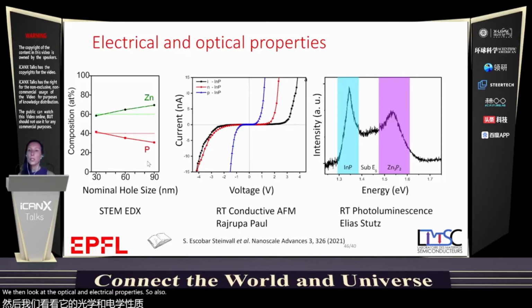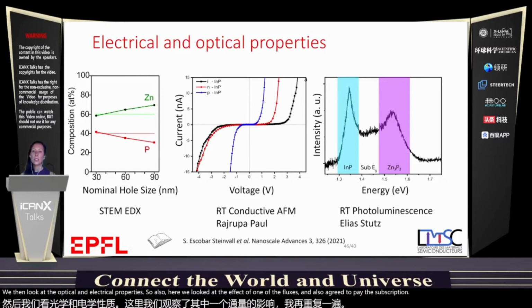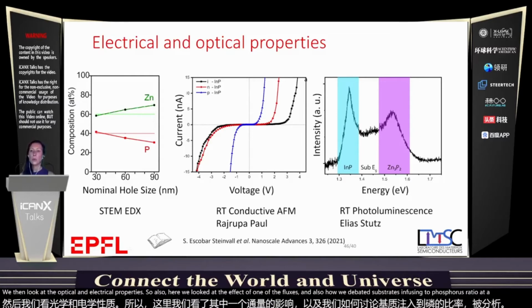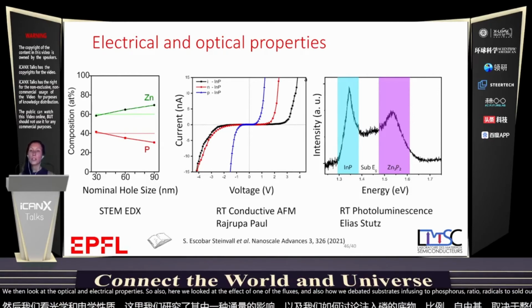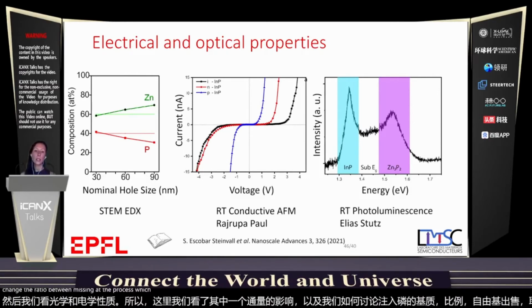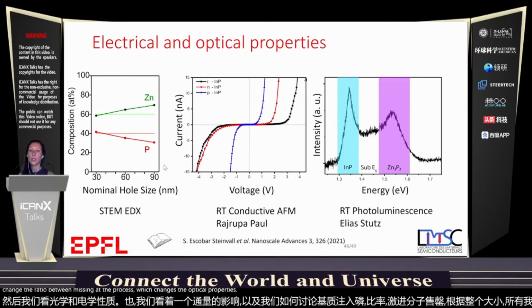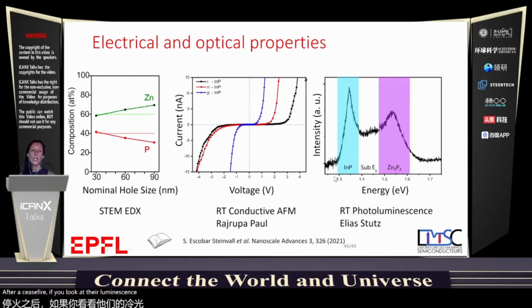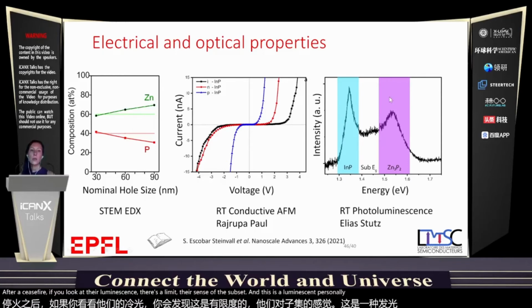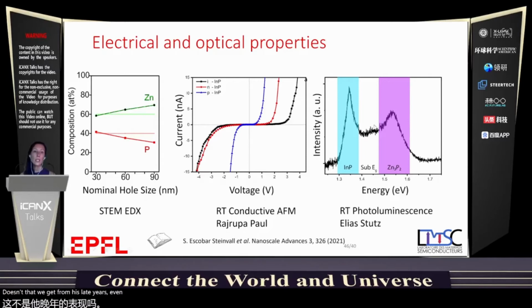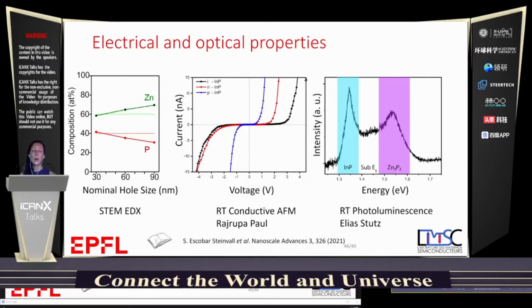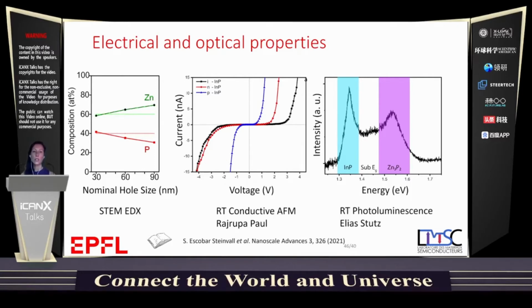Here we looked at the effect of the fluxes and also how we prepare substrates on the zinc to phosphorus ratio. We also saw that depending on the hole size on the substrate, we change the ratio between the zinc and the phosphorus, which changes the optical properties of the zinc phosphide. If we look at the luminescence, this is the luminescence of the substrate, and this is the luminescence of the zinc phosphide. This is a very high luminescence that we get from these layers, even higher than for the nanowires. So this illustrates that this is a very good way of producing high quality zinc phosphide layers.